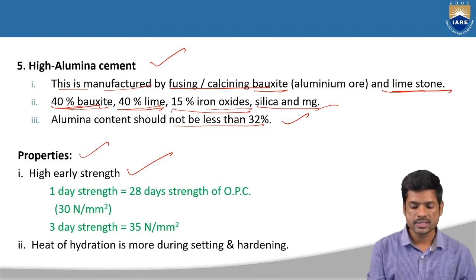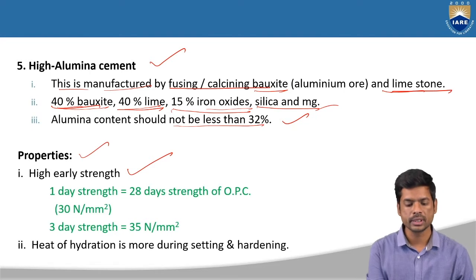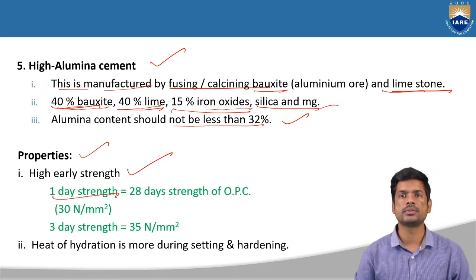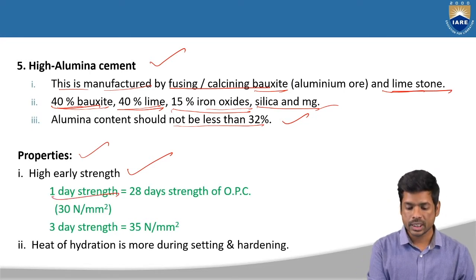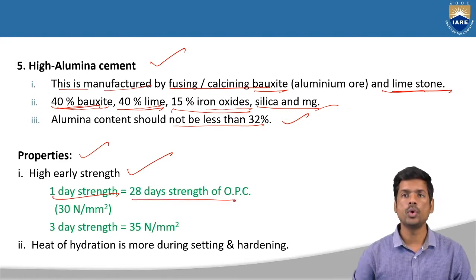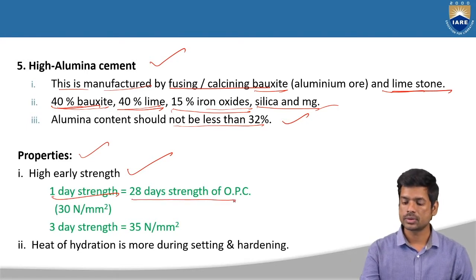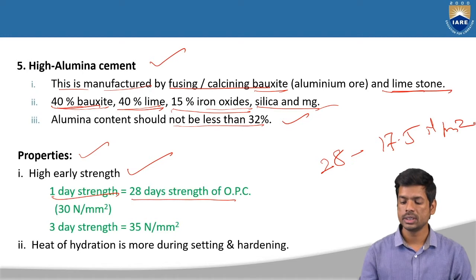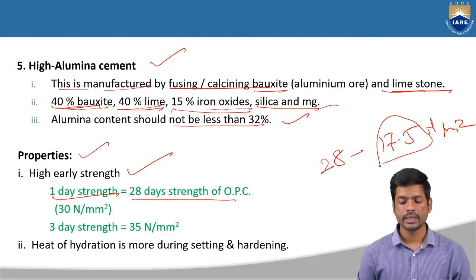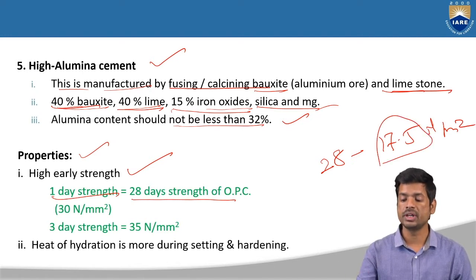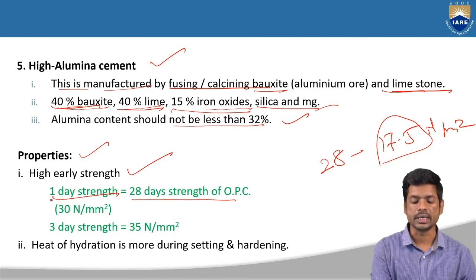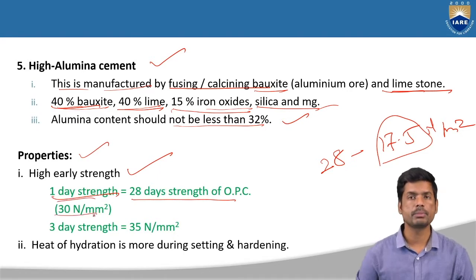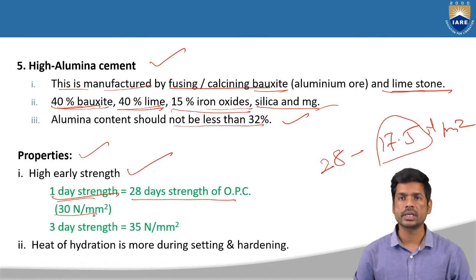Coming to the exact strength of high alumina cement, the 1 day strength is equal to the 28 day strength of OPC. In OPC we get almost 17.5 Newton per mm square as the ultimate strength, but high alumina cement achieves that in a single day, around 30 Newton per mm square within 1 day.